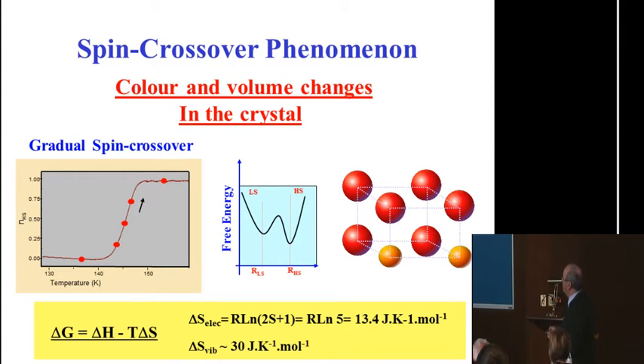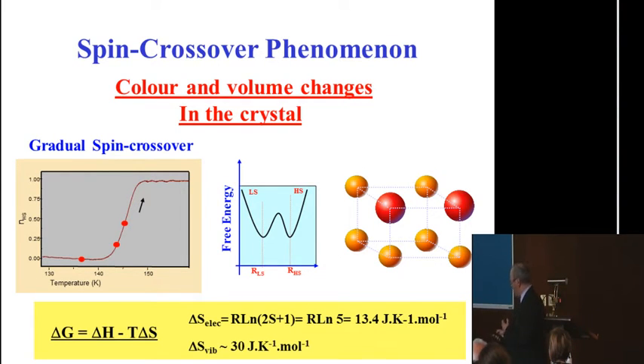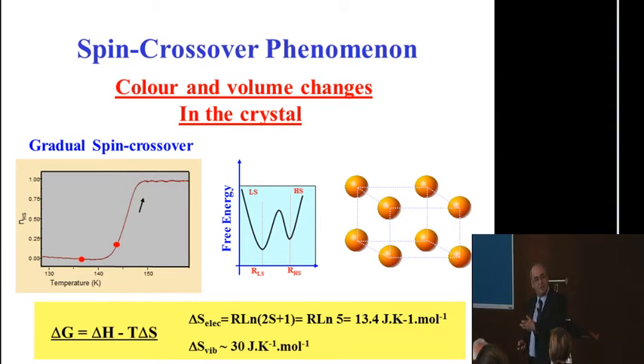Of course, if you wish to come back, you can come back, so you decrease your temperature, you destabilize it the other way, and then you have the switching to the low spin state. So the driving force is the entropy here. Through the entropy and temperature, you can destabilize your system, either from low spin to high spin, or from high spin to low spin, reversibly, okay?